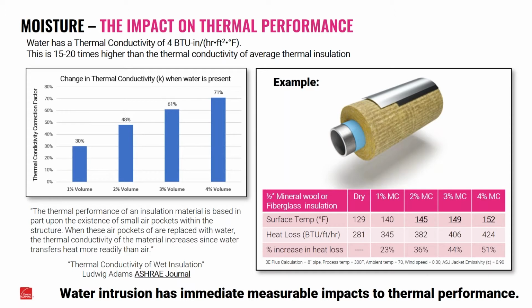Now, this particular example was done with just a 300-degree steam line, ambient temperature 70 degrees with no wind speed. And I know the jacketing here is aluminum, but the example that we used was actually more of like an all-surface jacket or kind of a white type jacketing. But anyway, it kind of shows the example of what the thermal impact of moisture in that system is. Again, if we had to tolerate that short term, maybe, but not something we want to live with for very long, because all that equipment that we've sized is anticipating a heat loss of about 300 BTUs per hour per foot, and all of a sudden we're dealing with 50% more than that, we're going to have a hard time with that equipment keeping up. So then that's going to create other problems.